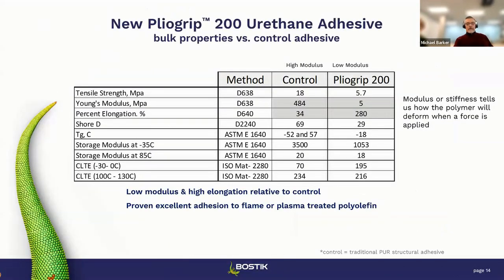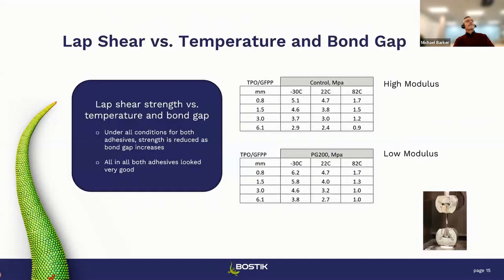So what we've done here is we've got 2 examples. We've got a high modulus adhesive, which we're going to call the control. And then we've got the low modulus adhesive, the Pliogrip 200. And a couple of areas that I wanted to focus on is the modulus, 484 megapascals for the control, and only 5 for the low modulus adhesive. Huge difference there. Percent elongation for the control is 34. Elongation on the Pliogrip 200 is 280. Those 2 constitutive properties right there are going to come to play and help us to get a more durable bond on the surface of the polyolefin.